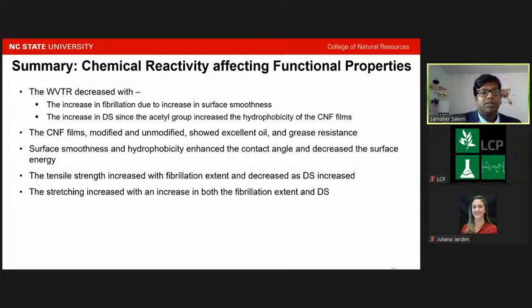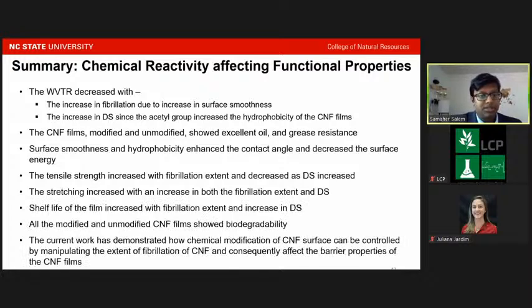The water vapor transmission decreases with the increase of fibrillation as well as with the increase of degree of substitution. The CNF films, modified and unmodified, showed excellent oil and grease resistance, surface smoothness, hydrophobicity, enhanced contact angle and decreased surface energy. The tensile strength increased with fibrillation extent and decreased as the degree of substitution increased. The stretching increased with an increase in both fibrillation extent and degree of substitution. Shelf life of the film increased with the fibrillation and degree of substitution. All the modified and unmodified cellulose nanofibrils showed biodegradability.